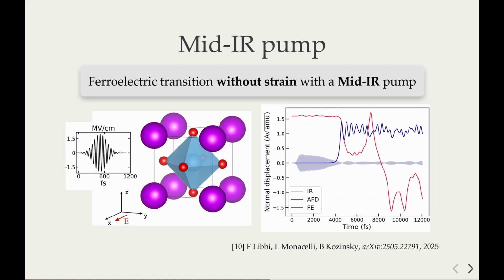We also performed a simulation with a mid-infrared pump, reproducing one of the two experiments I showed before. We pumped with this electric field at the same energy scale as the experiment. What happens is that after about 4 picoseconds, our system shows a spontaneous transition into a ferroelectric state—you can see this is the ferroelectric mode.